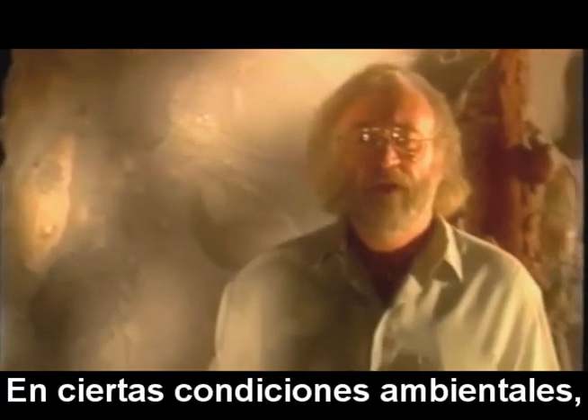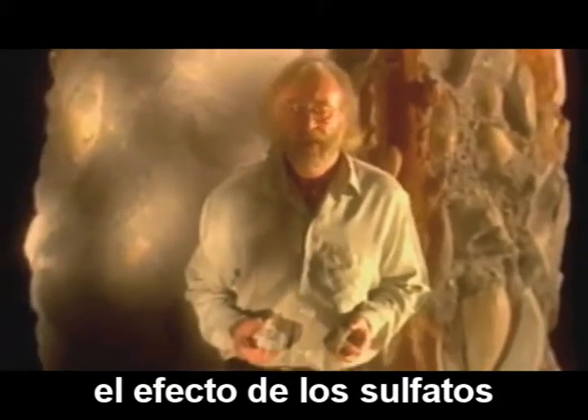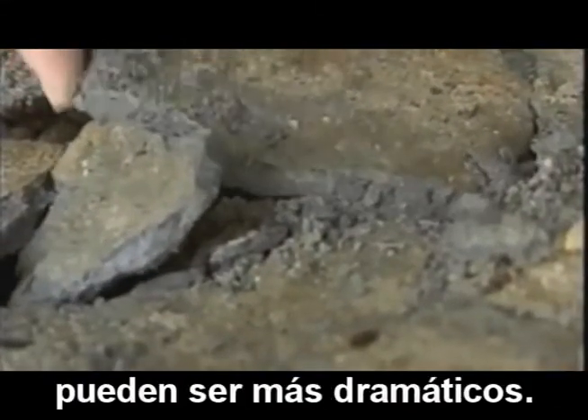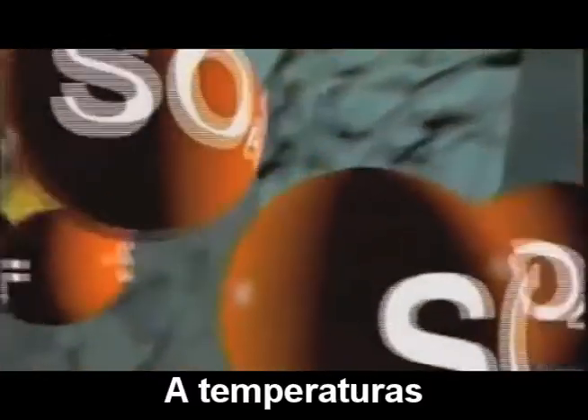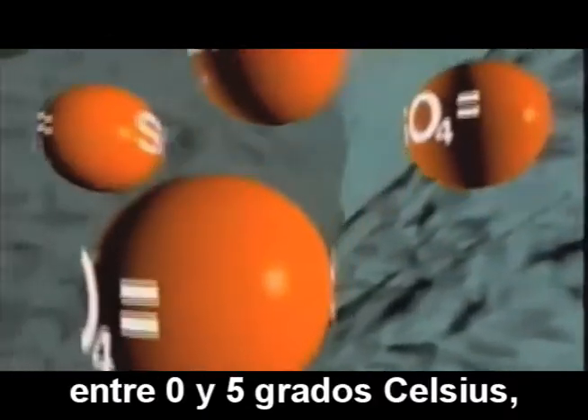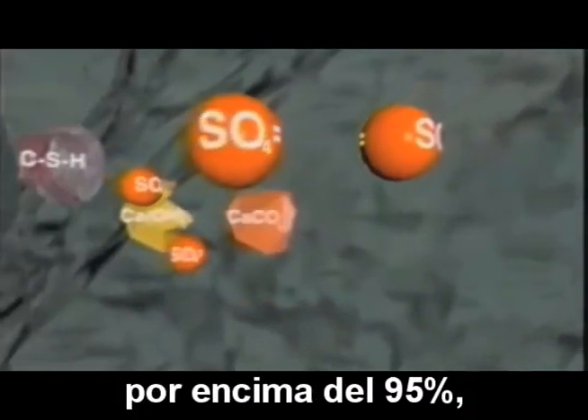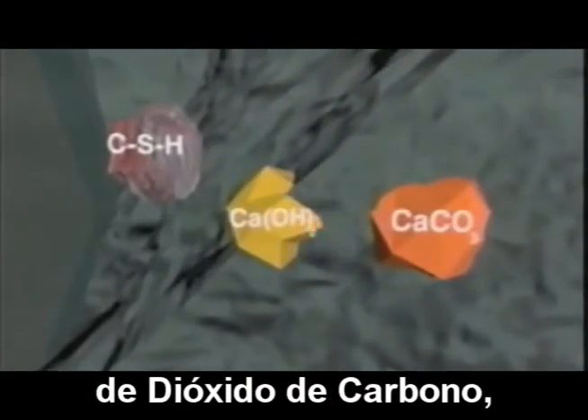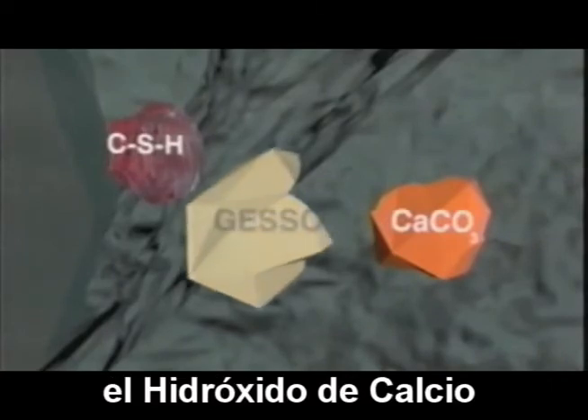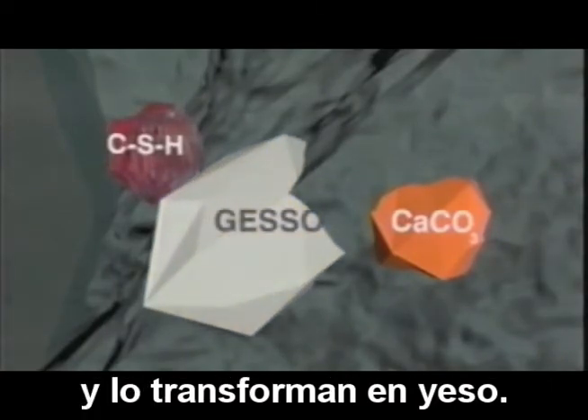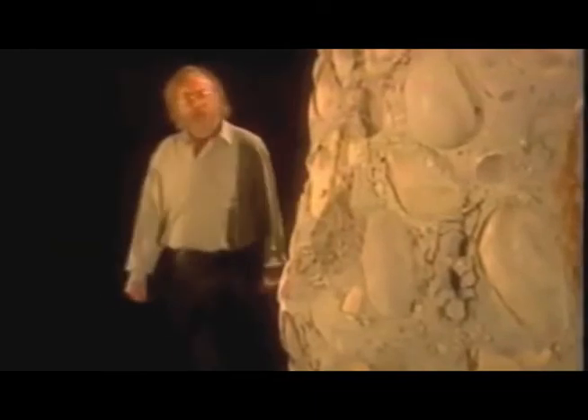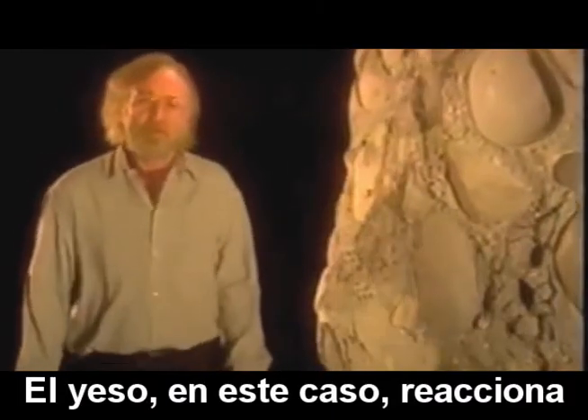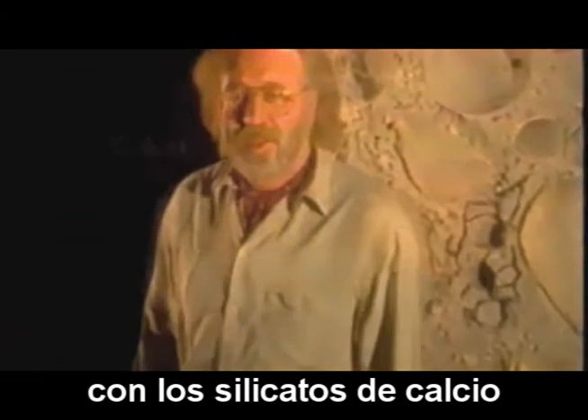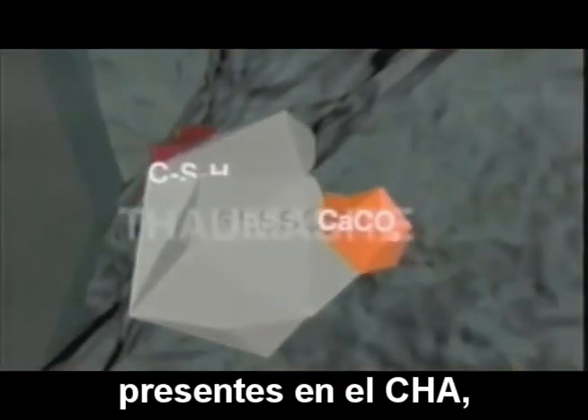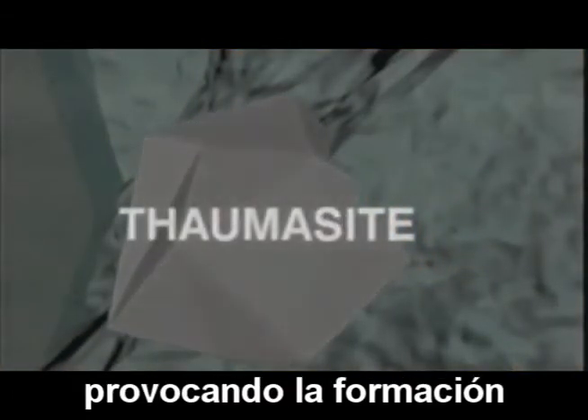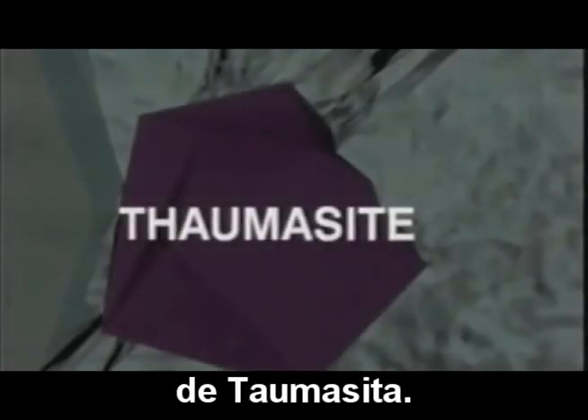In certain very special environmental conditions, the effect of the sulfate on the concrete can be even more dramatic. At a temperature of between 0 and 5 degrees Celsius, with relative humidity of over 95%, and in the presence of carbon dioxide, the sulfate combines with calcium hydroxide and transforms it into gypsum. The gypsum, in its turn, reacts with the calcium silicate hydrates, here indicated as CSH, and the calcium carbonate CaCO3, producing thaumasite.